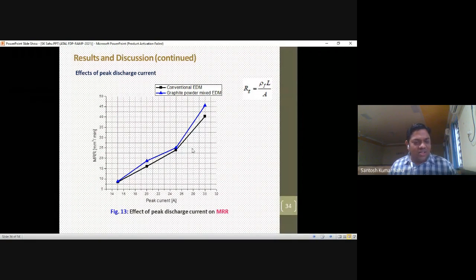So here MRR is a little bit higher in comparison to the conventional EDM. So the effect of peak discharge current results in an increase in the material removal rate, because the peak current is directly proportional to the energy input. So we have energy input at 15, 20, 25, 30. So more material was eroded from the workpiece, leading to improved MRR. The increase in MRR with respect to increase in peak current was found more in the case of graphite powder. That's what is shown in the figure clearly.